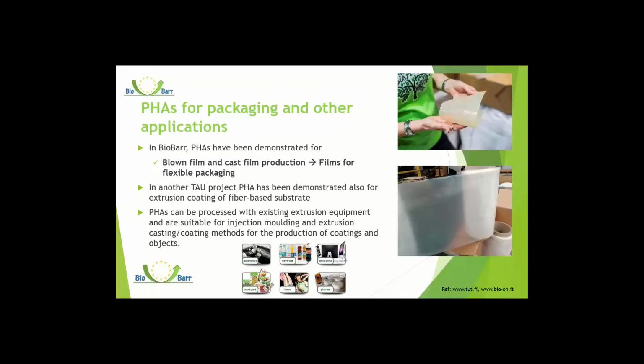So I'm getting to the end of my presentation, and I'm summarizing a little bit what we achieved. So in this project, we demonstrated different PHA grades for blown film and cast film production processes, and we were able to produce films for flexible packaging. Just to mention that in one other project, we have also demonstrated that now PHA is also used for extrusion coating of fiber-based substrate. So just as an example of how PHAs can be used in different applications.